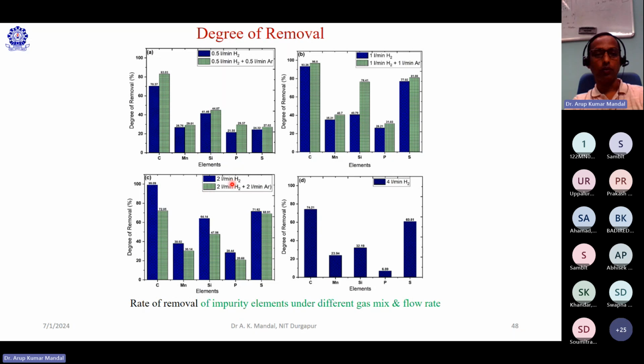But when we give 2 liter hydrogen and 2 liter argon, arc instability is observed. It means the hydrogen and argon combination is so high that it interrupts the proper arcing. We observe that in the case of the 1 liter hydrogen plus 1 liter argon combination, we got the optimum removal rate. But if you see 2 liter hydrogen, although the arc is unstable, more than 90% of the carbon is removed. It means for removal of the carbon, only hydrogen gas is enough. But plasma is required to reduce the sulfur, which is observed in the sulfur removal cases.